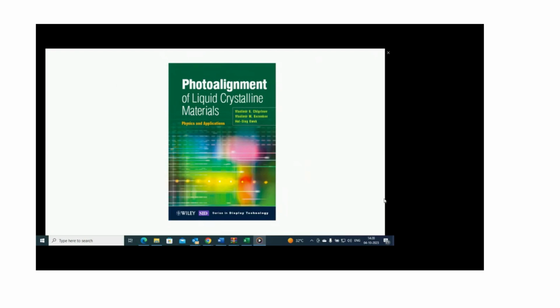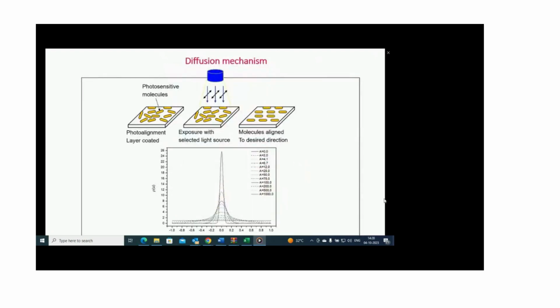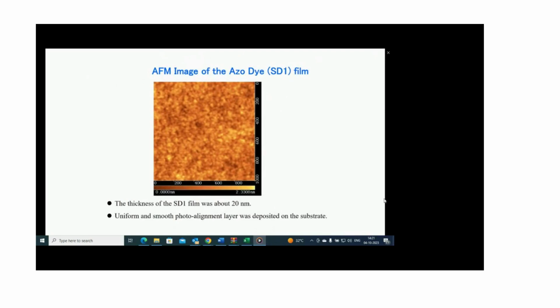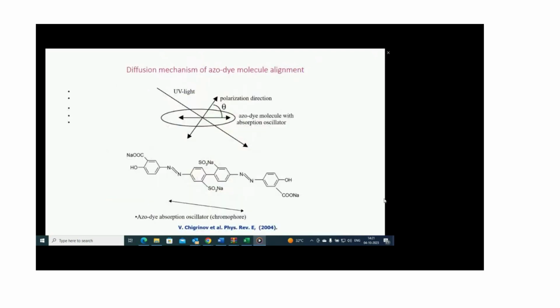We are now working on the revision of it. In this book, we showed that photoalignment is nanotechnology, nanolayers, and these nanolayers can effectively align liquid crystals. The thickness of the nanolayer is between 1 and 10 nanometers. And one molecule of azo dye can align 10 million more liquid crystal molecules in the bulk. Here you will see a very smooth atomic force microscope image of azo dye films, and the best azo dye which we can use for photoalignment is SD1.